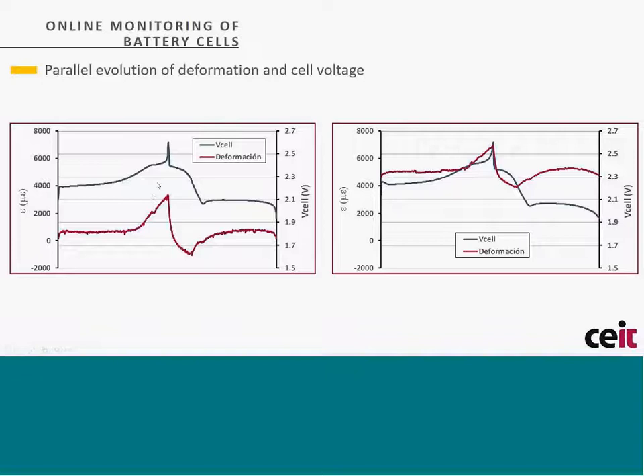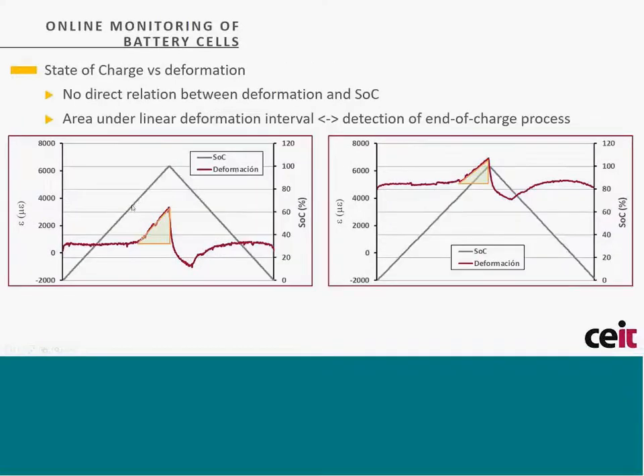So you can see that even there is a parallel evolution of both lines. We cannot directly detect what is the state of charge, but we can see this linear trend here, and if we get the area that is covered by this linear trend, we can estimate not the state of charge, but when the end of charge process is happening. So we cannot detect how it's been charging, but we can detect when it has finished the charging process.